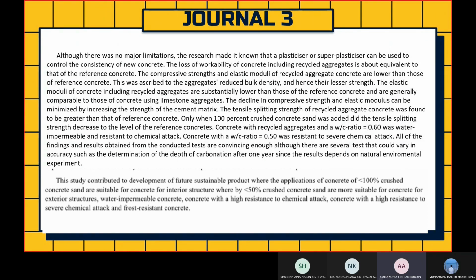The loss of workability of concrete, including recycled aggregates, is about equivalent to that of the reference concrete. The compressive strength and elastic moduli of recycled aggregate concrete are lower than those of reference concrete. This was ascribed to the aggregate's reduced bulk density and hence their lesser strength. The elastic moduli of concrete, including recycled aggregates, are substantially lower than those of the reference concrete and are generally comparable to those of concrete using limestone aggregates. The decline in compressive strength and elastic modulus can be minimized by increasing the strength of the cement matrix. The tensile splitting strength of recycled aggregates concrete was found to be greater than that of the reference concrete.